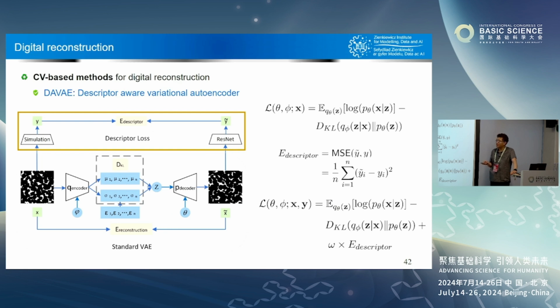But the problem is that until you examine the result, you simply do not know how good or bad your reconstruction quality is. Sometimes good, sometimes bad, I'd say. And the papers only show you the good one. So what we did is we embedded descriptors in this reconstruction process as part of the loss function. In this standard VAE, you always have a loss function at the end, which gets backward propagated into your neural network. So we could easily build the statistical descriptors within that loss function.